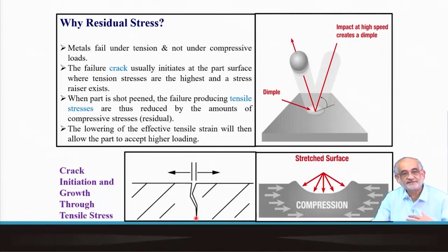So, in the event of either having a possibility of such crack formation, or in the worst case, a crack already exists even before we have done this operation, in either case, creation of such a state of stress which is acting towards each other will actually diminish the possibility of this crack opening further or leading to any amount of failure. So, that's the main technological advantage and objective for which residual compressive stress is created by shot peening.